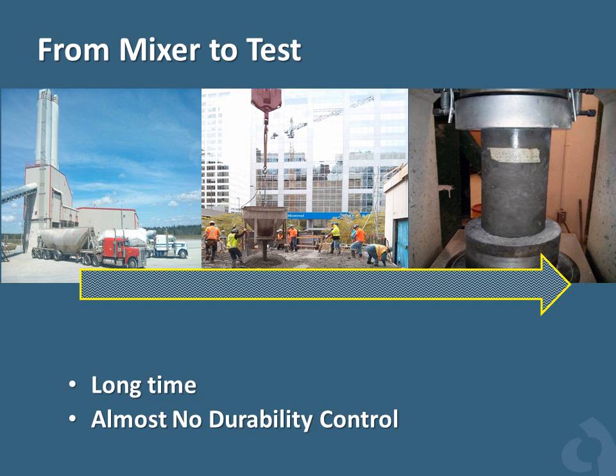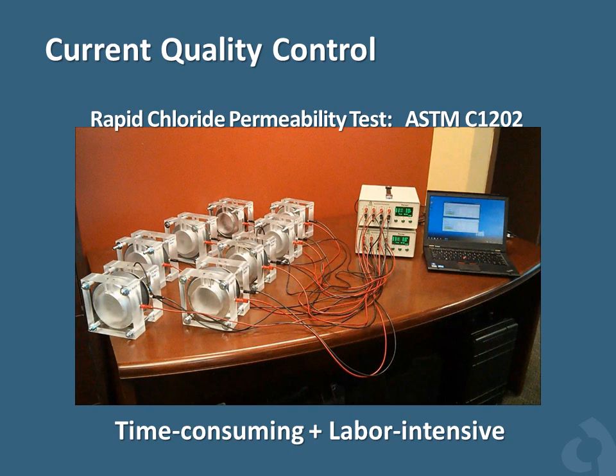Compressive strength in concrete is not necessarily an indicative test for durability of concrete. The only other method employed in some major projects is the use of rapid chloride permeability tests, informally known as RCP tests. The RCP test is a widely accepted approach for durability assessment of concrete material. In this test, the electrical charge passing through concrete is used as an indication of the concrete's ability to resist chloride ion penetration. The test should be carried out on 28-day saturated samples.